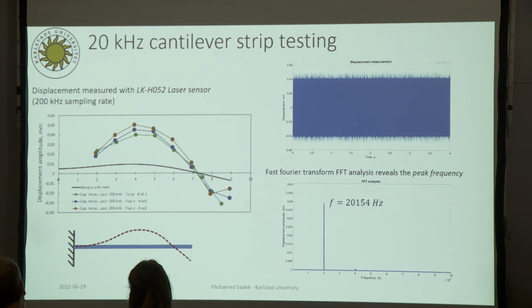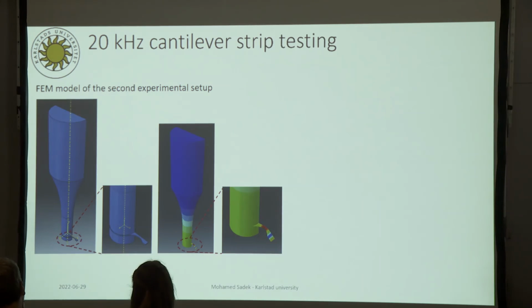Anyway, at that time, we also came up with a new idea about a new test setup where we got rid of the horn at the bottom. And what we did is we tucked the specimen into the horn instead. So we have one wavelength here with this small specimen tucked in here. And because it's so small, it's okay. It works. And it's a much better system. It includes fewer parts, fewer problems, and it should be smoother to use.